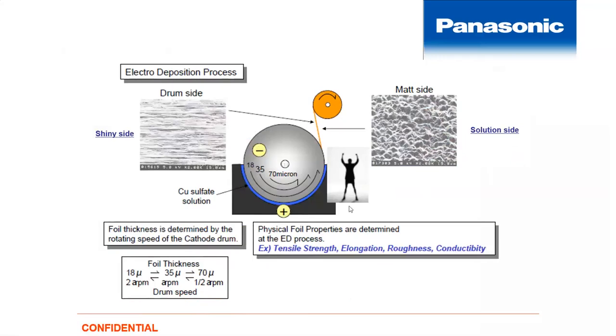You can see the thinner the copper, the faster this drum can go, and the thicker the copper, if we're going to 1 ounce, 2 ounce, then the drum has to slow down quite a bit to allow the time to plate onto that. And the copper manufacturers control that. They control the baths, and all the tensile strength, the elongation, the roughness, that's all being done in that manufacturing process.